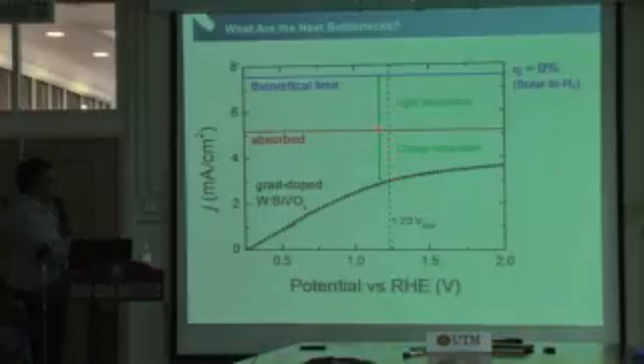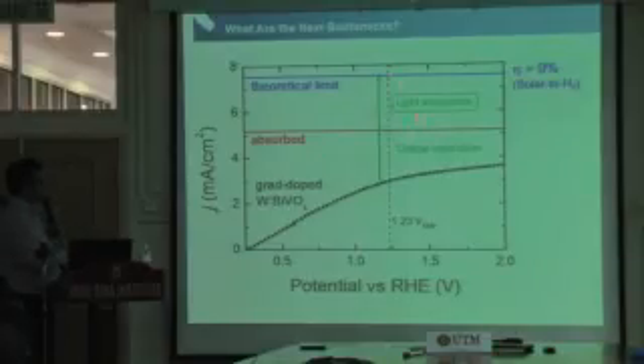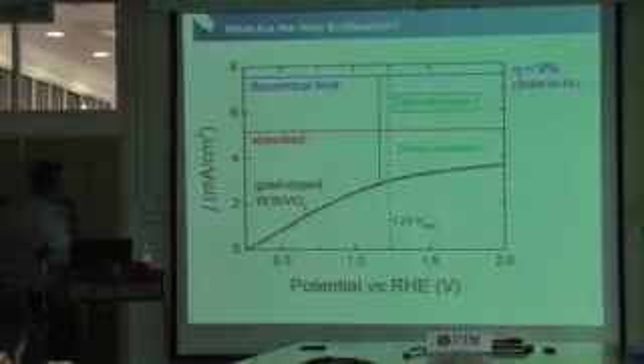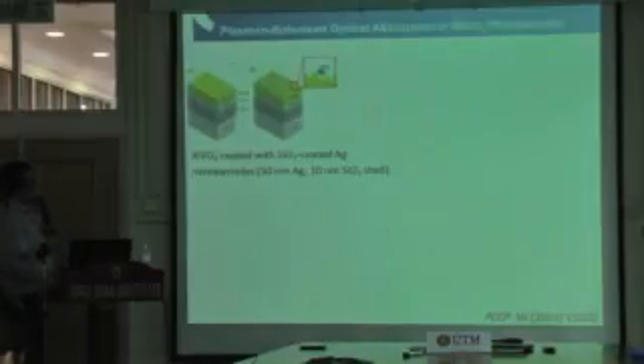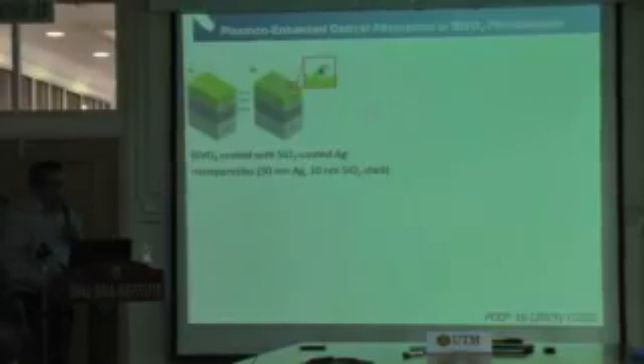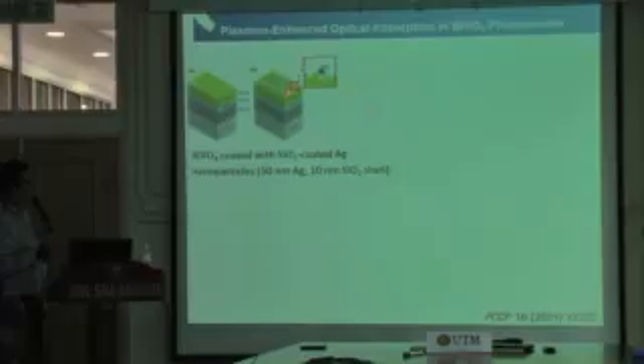But what is now becoming more important is the difference between the blue line and the red line. And this is simply because of inefficient light absorption. We lose about 2.5 milliamps per square centimeter in our sample just by not absorbing light efficiently. So we started some activity on plasmon-enhanced optical absorption in bismuth vanadate photoanodes. We put silicon dioxide-coated silver nanoparticles on the surface of our bismuth vanadate, with the hope of having plasmonic resonant absorption in our bismuth vanadate.